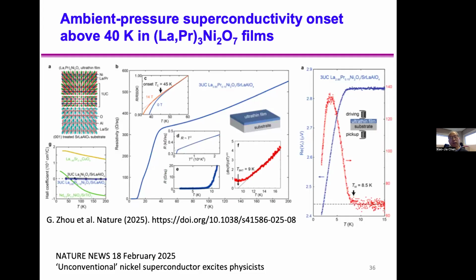Very recently, just yesterday, Nature News mentioned that an unconventional superconductor excited physicists. Why? Because in the nickelate, it shows an onset temperature like 45 Kelvin. You can see here that the zero resistivity state is reached below 10 K. Also, they give an AC susceptibility measurement. I think this susceptibility measurement shows the transition below 9 Kelvin. This material was reported to exhibit superconductivity at high pressure, but now its ambient pressure superconductivity is reached.